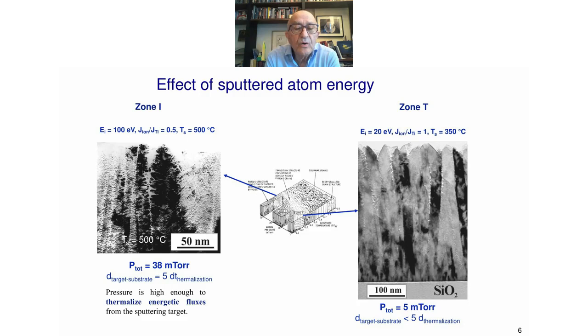So here I demonstrate the zone 1 structure, which is obtained at 38 millitorr, of titanium nitride deposited at relatively high temperature, 500 degrees, and a high bias of 100 eV. And you see we have columns with a lot of pores between the columns and within the columns. So this is a way to produce extremely porous films, if you like.